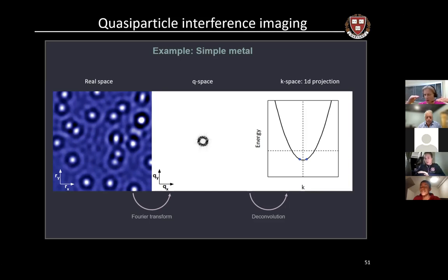And the one that was not on the conducting substrate had been gated by the STM tip itself. And so it was actually exhibiting different physics. And what we ultimately showed, we looked at antimony, which is a topological semi-metal. And in antimony, we were able to observe both the Landau levels and the quasi-particle interference in the same material. And it's a semi-metal, which means it's a pretty good conductor. And so it didn't have this tip gating effect. And we found that they agreed well with each other.